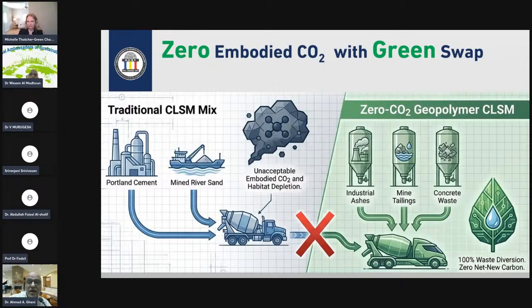So for the binder, we will introduce something similar to geopolymer, but we will use a material that has never been used before for geopolymer because it cannot work for real concrete. And I will touch base on that shortly. At the same time, rejected or off-spec cement, rejected for many reasons, I will explain that in the next slide, as a binder. In terms of the filler, we will use tailing, any leftover from mining here, and the industrial waste as well, to come up with the green, controlled, low strength material.